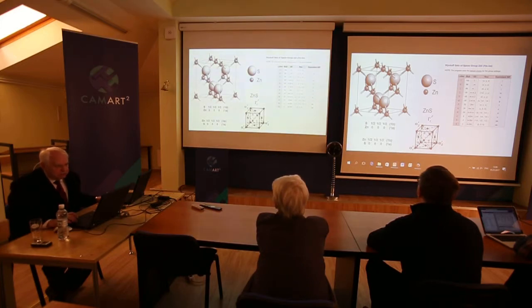This is the sphalerite structure, very simple. This is a face-centered cubic lattice. So for crystallographers, the multiplicity must be divided by 4. So this is 1A, 1B, or 1B, 1A. These are 2 equivalent descriptions. Face-centered cubic lattice. Next.